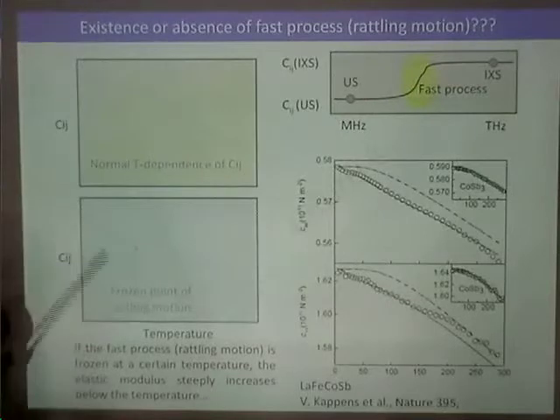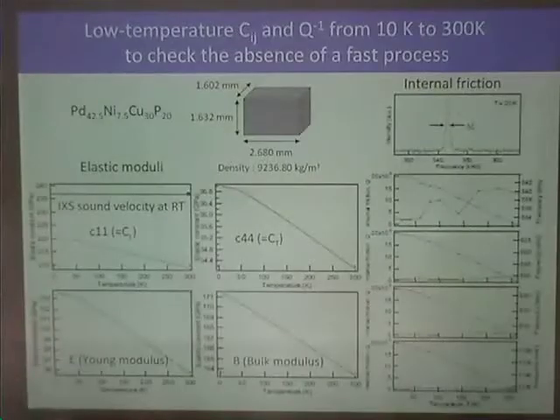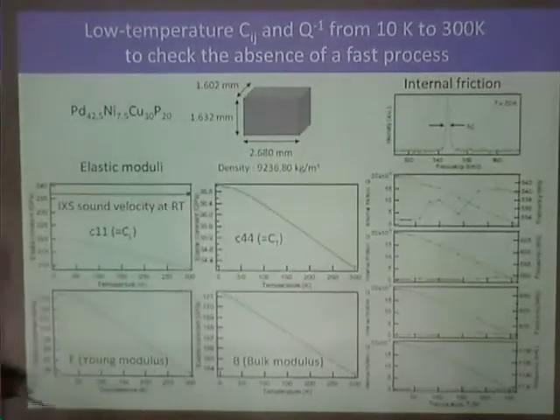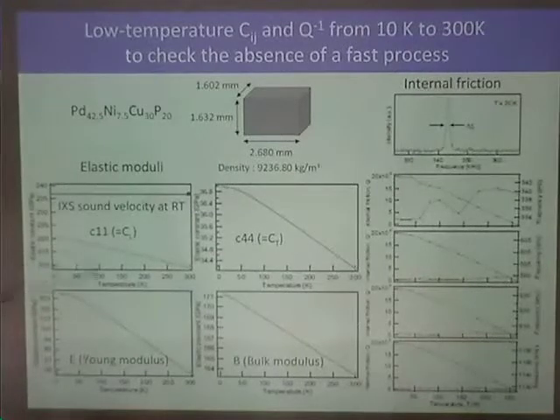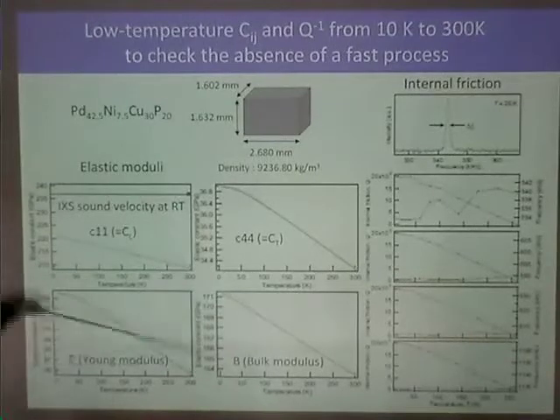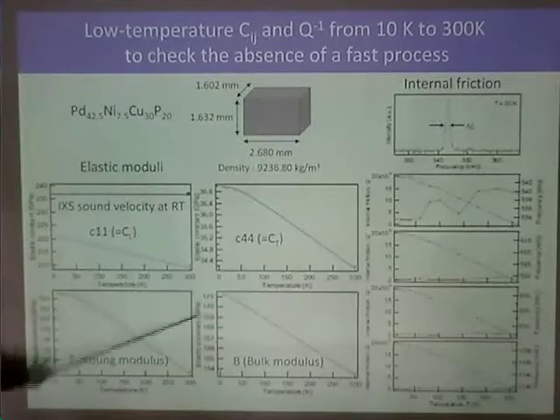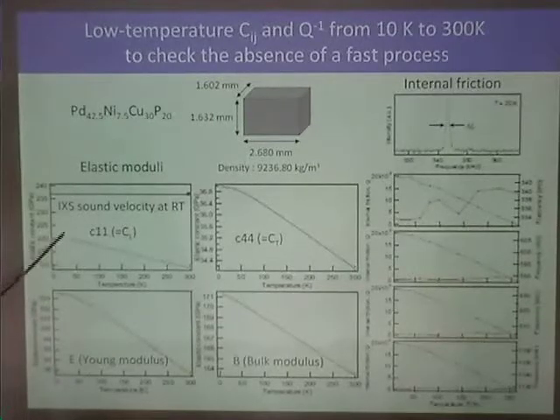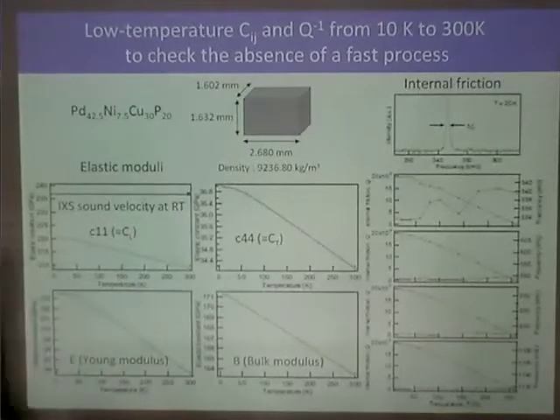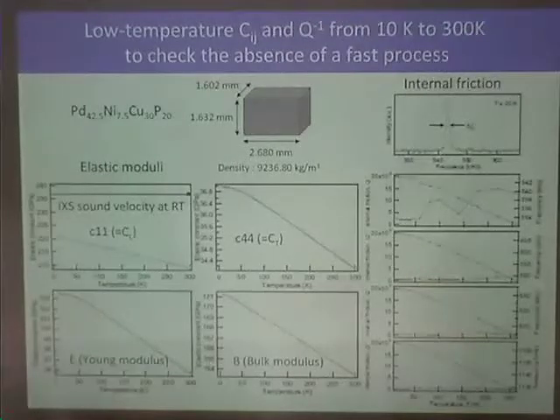Therefore I have to check whether we can observe this or not. So we have performed low temperature elastic constant measurements from 10 Kelvin to 300, room temperature. So we have C11, Young modulus, bulk modulus, C44. But most of the elastic constants monotonically decrease, with slightly strong temperature dependence but no obvious defect. Therefore, probably the faster relaxation process does not exist in this matrix.